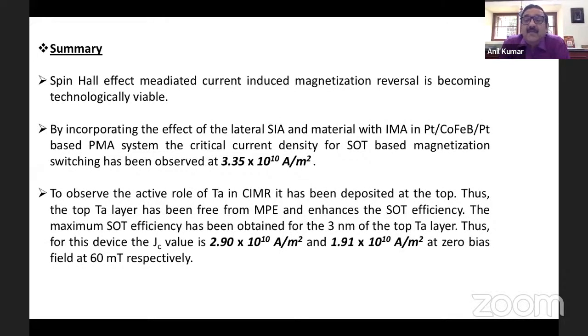Yeah, the thing is that now we are exploring the topological material, because materials with heavy spin orbit interaction. So now we are exploring the topological material which has got very high spin orbit interaction. And also, even further, we can tune this by tuning the interfacial properties. Finally, there's something called a Dzyaloshinskii-Moriya interaction at the interface. That depends on the interface quality. So we need to further improve the interface quality, and that's what we are trying. And moving towards fermions.